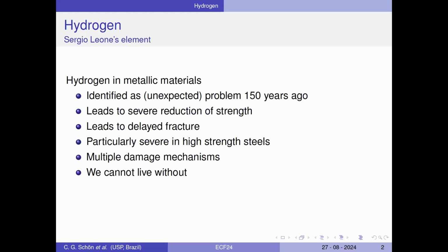But just to remind what we know about hydrogen and materials. First of all, it's not a new problem, so it's already identified some 150 years. Of course, we know it brings a decrease in strength, so it leads to delayed fracture, which is even worse in service because you produce a component and suddenly it breaks, so it's not very funny to have this kind of problem. It's particularly severe in high-strength steels. So the very steels that we use for good purpose are the most susceptible to hydrogen embrittlement.